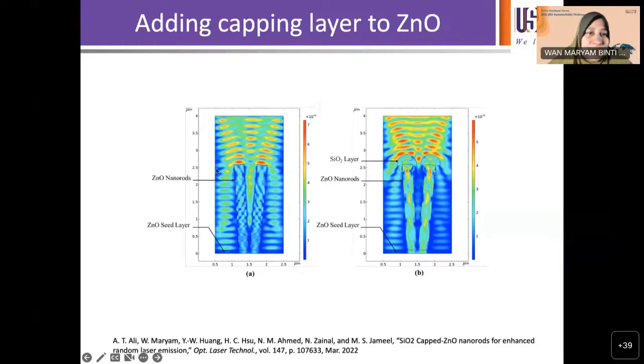And we made sure that this axis is the Z direction, or basically the C axis orientation, when you consider the material itself grown that way. What happens is when we have this light confinement, you have the waveguiding actually happening inside the zinc oxide nanorods compared to when you have just the bare one. The bare one has leaky modes, as you see here. When you have the very light color of red, yellow, it's a very strong confinement, strong modes. So when you have the propagation inside the rods, this will give much stronger light confinement, basically. In simple terms, this is what it means.